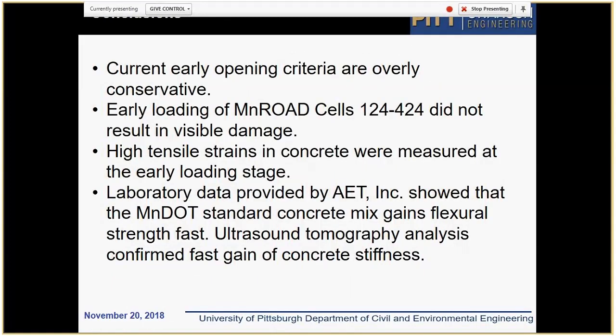So basically, that's what we've done so far. We went through the data provided to us from MnDOT. We had difficulties and we still have difficulties explaining some of them, but it looks like we're making progress, and now everything is starting to make sense. And the most important observation is that some of the conclusions that you can find in the literature and some of the experience people have with other mixes are not applicable to stiff mixes that are used for slip form pavers.